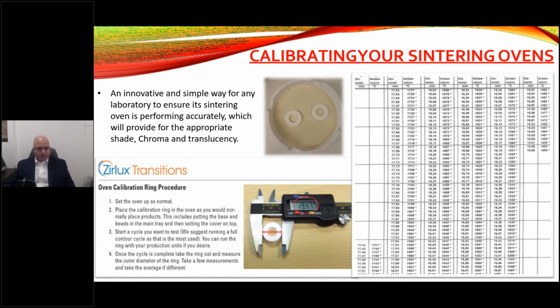And whether you have a silicon carbide sintering oven or a molybdenum sintering oven, both function a little bit differently. Some maintain heat better, some not, but in order to get the chroma and the translucency, as well as the incisal that you're looking for, the smart incisal that's been designed for this, the temperature really has to be spot on in order to get the best results. And I'll show you some samples of what a 20-degree difference will look like.